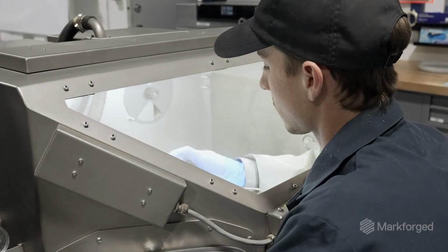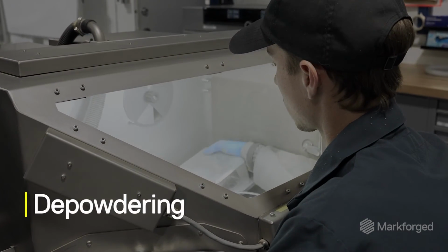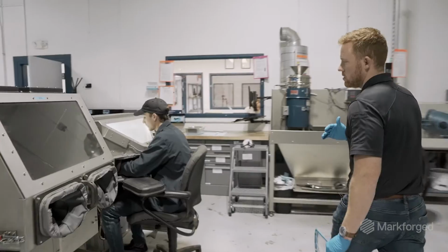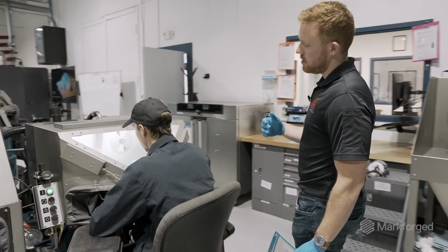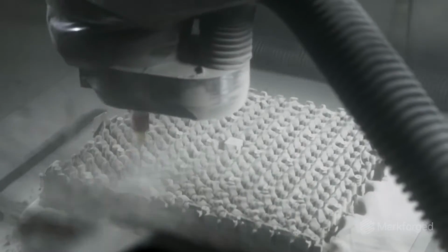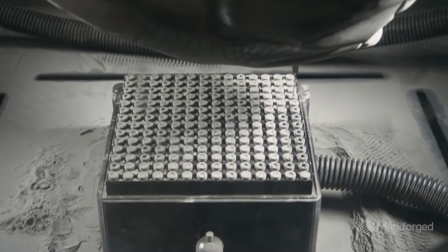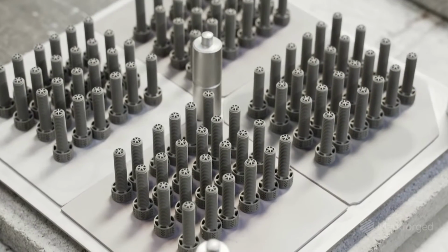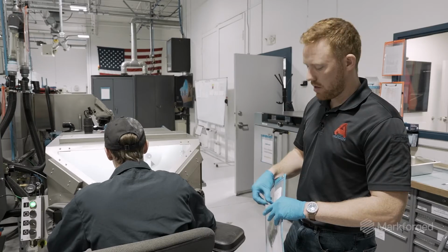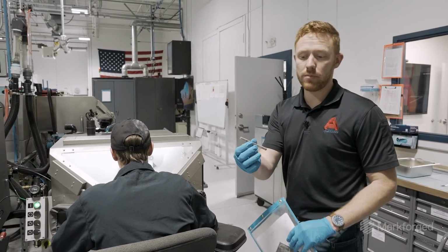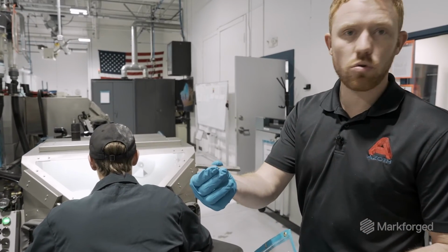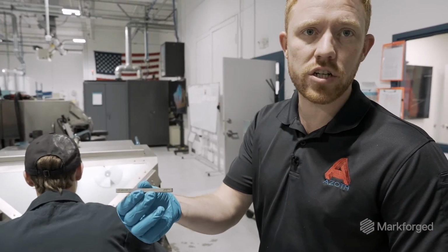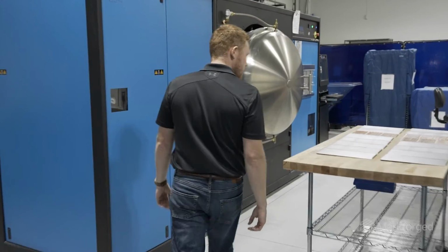After that, we'll go through a depowdering step. So we can check that out over here. During depowdering, we're gonna blow off all the loose powder on the components. Then we vacuum that up to be recycled and reused in future prints. And when they're done with depowdering, it reveals like a green geometry. And a green geometry is about 20% oversized in every direction. We can then take that to the furnace for sintering.